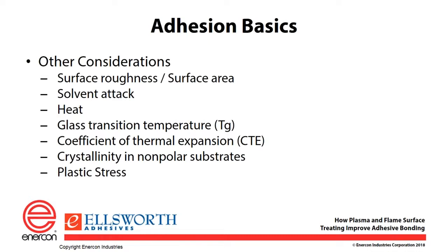Heat is an important aspect when thinking about adhesion. If you use heat to cure your adhesive, it frequently will end up with a higher bond strength because you drive the reaction of the adhesive further than it might have been driven under ambient conditions. Heat can also help with substrate issues. For instance, crystallinity in nonpolar substrates can be improved by heat. Heat can also give you better diffusion.